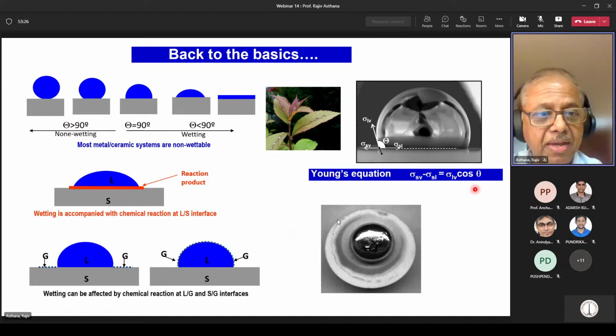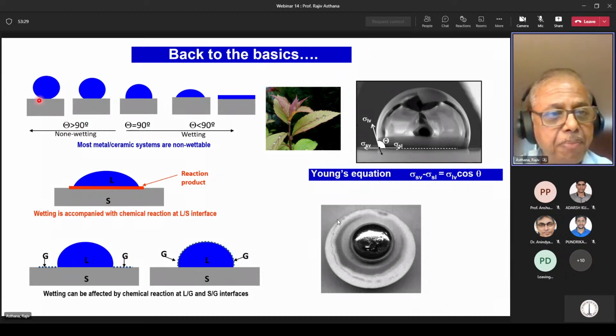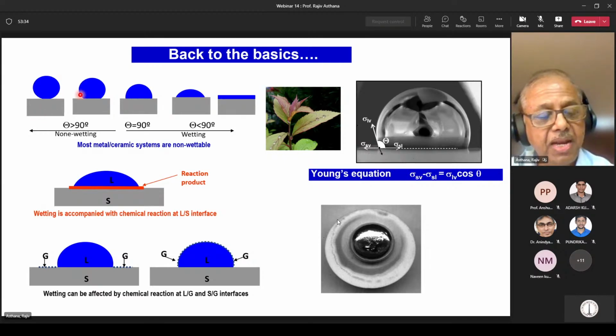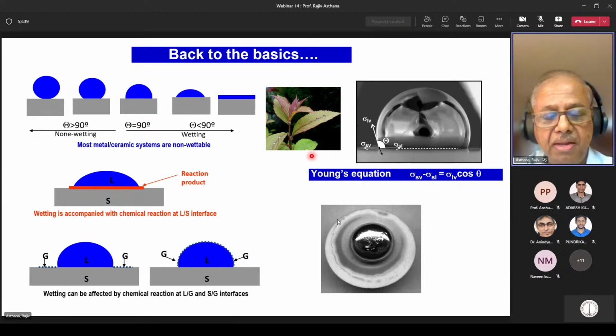So just for a moment, going to the basics for some of the students who may not be familiar with the topic, when you have a liquid droplet, a very teeny droplet that you bring in contact with the solid surface, the liquid spreads and then it stabilizes. And typically, if you have, let's say, water on a clean glass slide, it will take a few microseconds for the droplet to stabilize and give you an equilibrium shape. For high temperature systems, the liquid droplet will keep spreading for half an hour or an hour or more. And that is mainly because of the reactions and interactions that take place between the liquid and the solid.